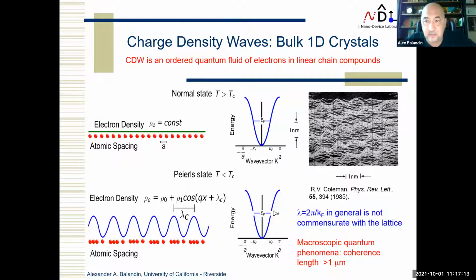Okay, so what are charge density waves, just in case some people have not heard about them? If you take certain metals which have quasi 1D crystal structure, it can become energetically favorable for them, when you start cooling them down, to develop a lattice distortion, which is then accompanied by periodic modulation in electronic density. This was essentially noted initially by Peierls. And he thought that maybe it's not too practical, and as far as I understand, he didn't even publish a separate paper. He entered this paragraph in his textbook.